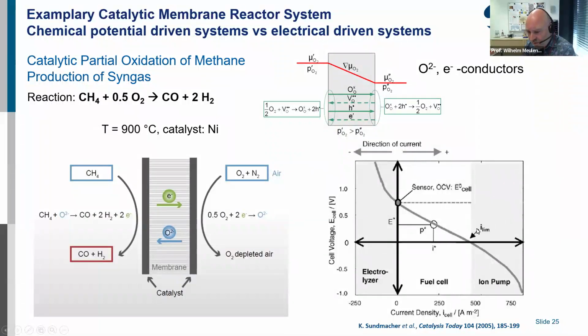But then if you look to this point here, I lim, you have one point where you have no outer voltage, but in this case, you need the mixed conducting membranes, which is able to transport oxygen ions, but also which have some electronic conductivity for electrons. And one possible application, what you find in literature, and I guess in this field is the most literature available, is the partial oxidation of methane, where you have on one side air, you split the oxygen to an ion, transport it through the membrane, and it partially reacts with the methane for production of a syngas.